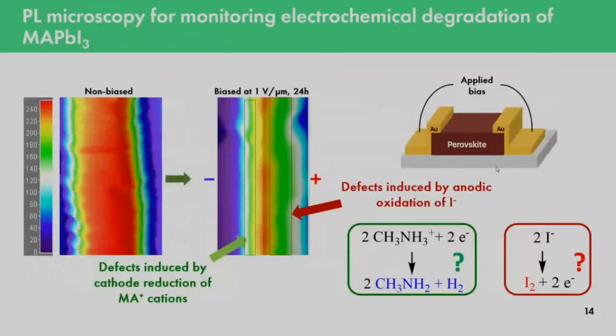To check this, we decided to make a PL mapping for the same lateral device biased for 24 hours already. So previous devices were biased for several hundred hours, this one for just 24, to observe the starting changes. And yes, we observed the depletion of PL intensity, and this depletion is probably influenced by the appearance of some defects along both the cathode and anode, which could confirm the appearance of some redox process.